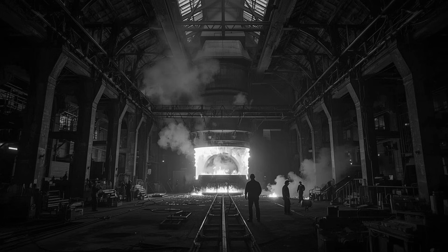The steam vent was the trigger. Positioned badly, exhausting into a space that connected to the chimney base, it had introduced a massive thermal disruption at exactly the wrong moment. The steam pulse didn't need to be sustained. 4 seconds was enough. It condensed, created a dense column of cool, moist air, and tipped the pressure balance past the point of recovery. But the real insight came from understanding the interaction between all 6 furnaces.